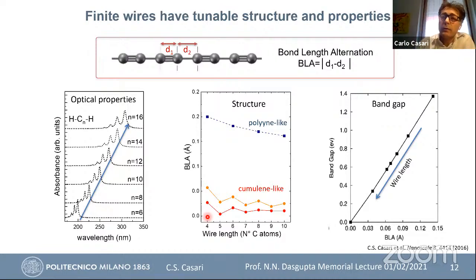In the same way, the band gap in between these two, because ideally I showed you that one is semiconducting, the other one is metallic, but in the real case, when it's finite, you have a band gap that depends on the BLA value. So by decreasing the BLA, you decrease the band gap from semiconducting toward a zero band gap structure.